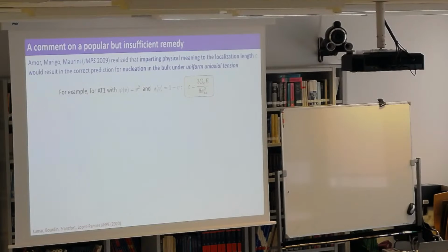If you choose the AT1 regularization, and then you use this function for the degradation, then if you fix epsilon, the regularization parameter, to the tensile strength, then this seems to capture tensile strength correctly in 1D, right? When you do uniaxial tension. So somehow these equations not only give you the right propagation and nucleation from existing cracks, but maybe, right, they're able to do more. But okay, if we use this, there is a problem with this.